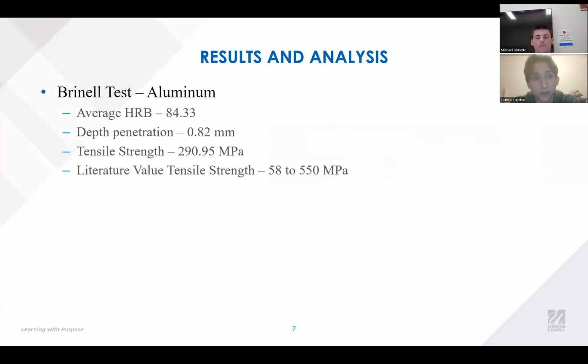So this is super important because for the Brinell test, we actually use the equation that the TAs give us, which relates the diameter of the impact crater and the overall tensile properties of the material that you're pressing into. And so the Brinell test is very interesting because it gives us an array of different values. But mainly for our results for the Brinell, we got pulled aside by the TA and he did the test for us. And then we got data from that.